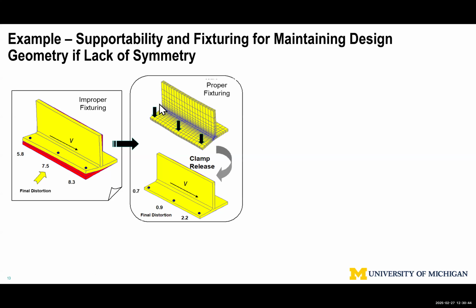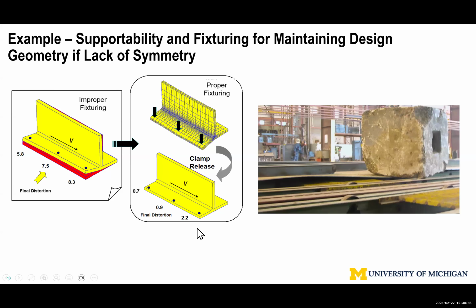For illustration purposes, using a computer model, we can demonstrate that just doing this, you get a very significant reduction, 0.7, 0.9, 2.2. This was validated by measurements. During this process, for this particular case, we asked if you had to use clamping. On the phone back then, we didn't do Zoom often. There was no Zoom. They said, yes, Dr. Dong, we clamp, we tie down.